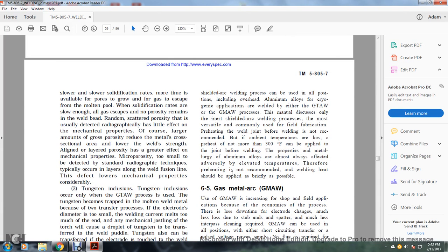Slower solidification rates allow the pores to grow and the gas to escape with the molten pool. If the solidification rate is slow enough to allow all the gas to escape, the non-porous metal remains in the weld, or scattered porosity may remain, which is usually detected radiographically. It has an effect on the mechanical properties.